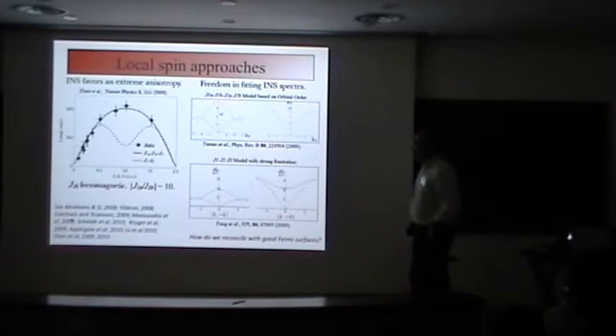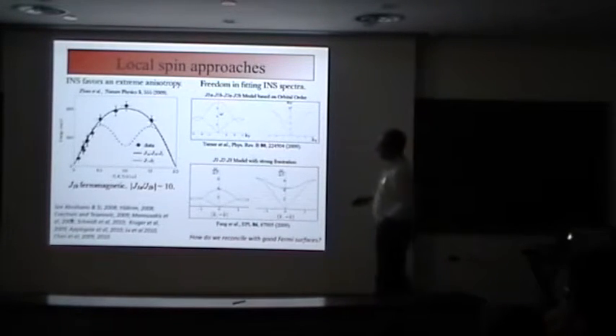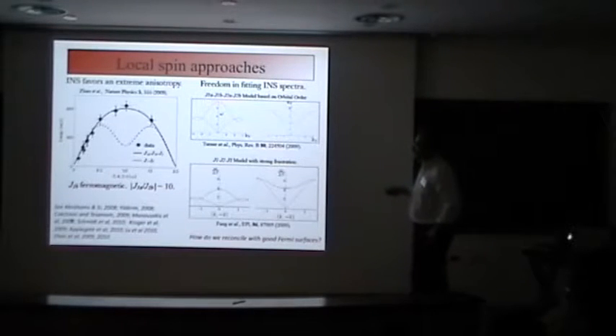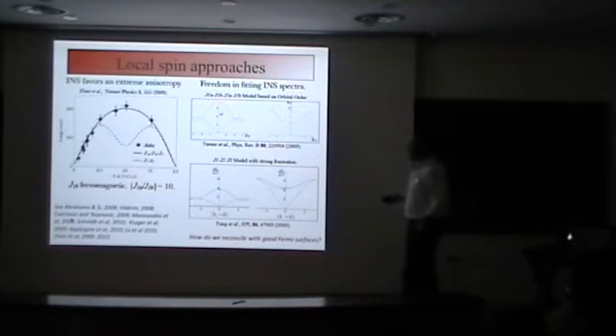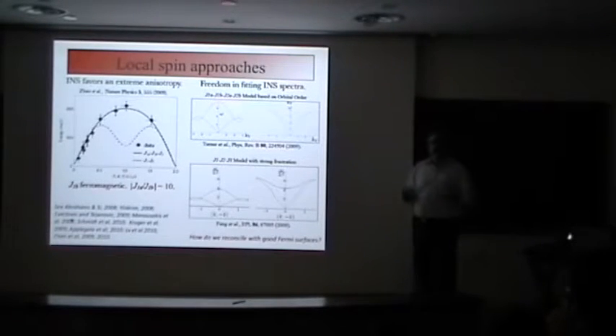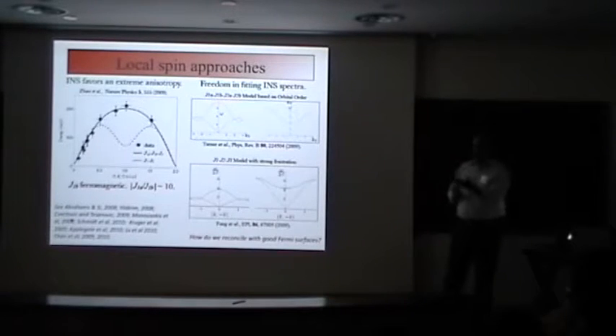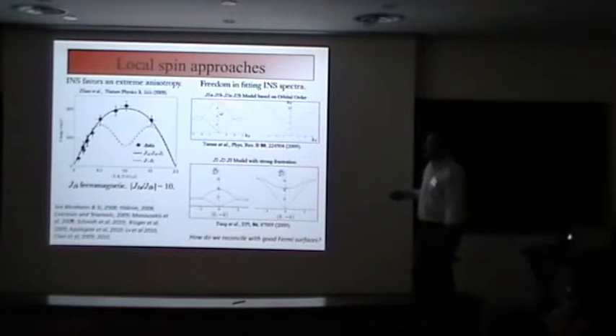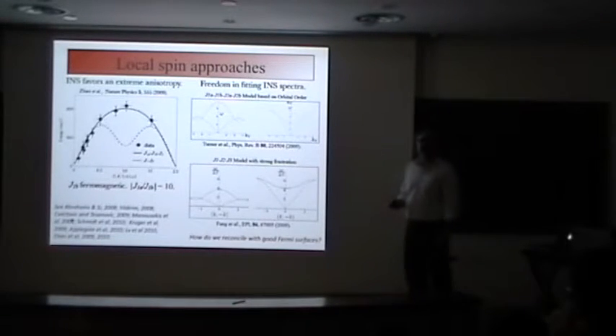One can fit the dispersion from neutron scattering, and particularly along the 1-1-1 direction, in the frustrated J1, J2 model—which is trying to decide if it wants a square lattice, a pi-pi wave vector, or a pi-0 wave vector—the depth of this minimum is controlled by how close you are to the critical point.